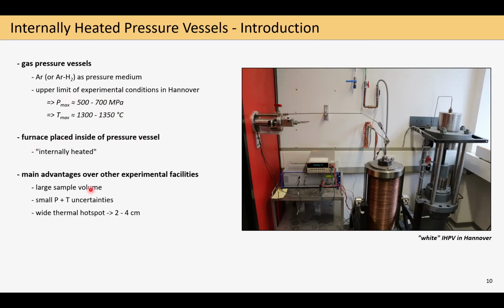And with respect to other experimental facilities covering similar pressure ranges, for example, cold seals or piston cylinders, IHPVs have the huge advantage that we have relatively large sample volumes available. The uncertainties on pressure and temperature are relatively low since we are measuring both parameters directly, and we can maintain relatively wide thermal hotspots in the range of 2 to 4 centimeters.